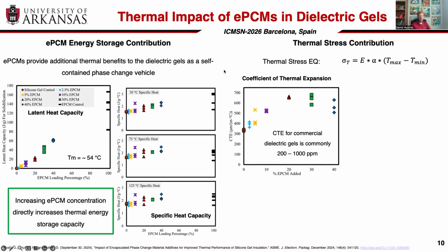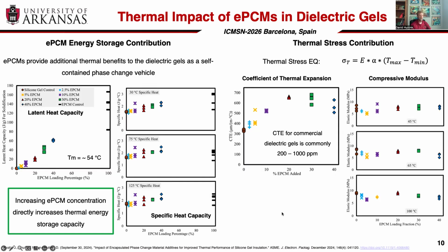But the other side of the equation too is how does this affect the thermomechanical aspects of the system? When we think about electronics, often thermomechanical issues are top of the line in concerns about reliability because of the thermally induced cycling fatigue that can take place. And these silicone gels are used often because they're very soft, and so they don't impart much stress onto that, even though they have a high CTE, because it's really a combination of both the stiffness and the CTE, or thermal expansion coefficient, in doing this. So because the ePCM particles do expand through that melt cycle, they do exhibit a significant increase in the CTE for the materials. However, the stiffness part, since we're having a relatively minor addition of particles in terms of the loading percentage, we don't see a big change in the stiffness of the materials.